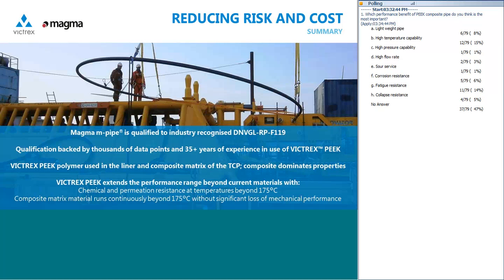Most importantly, chemical and permeation resistance excel really with PEEK up to and actually beyond 175 centigrade. The matrix material will actually run continuously above that without significant loss of mechanical properties. So you have a very high level of security in choosing this material combination.